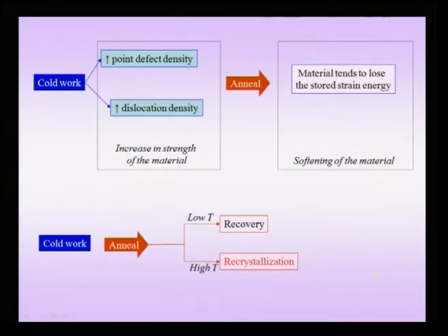Now when you anneal such a material, that means heat it to some temperature and hold it, the material tends to lose the stored energy and tries to come back to its original state. That means a state wherein the defect density is small. If I am doing cold work, I have an increase in defect density leading to an increase in strength of the material, and after annealing the material becomes softer and the dislocation density would decrease.